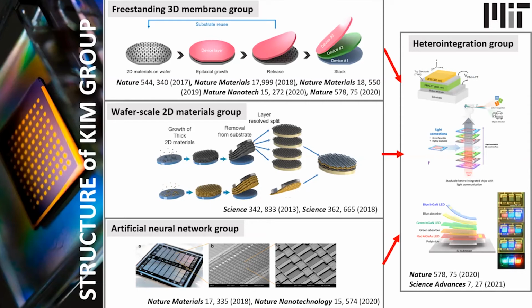What's so special here? 2D material is ultra thin and flexible. At the same time, this is inorganic material. But so far, scalability has been an issue for this material. So my group has been working on scaling up this 2D material at the wafer scale. Then we successfully developed a way to stack this kind of 2D material in one place at the wafer scale.